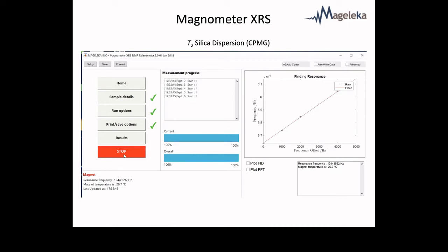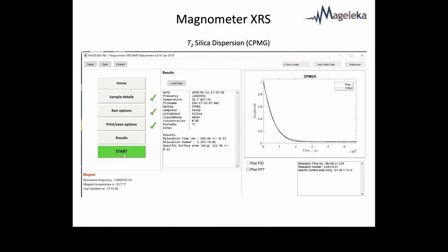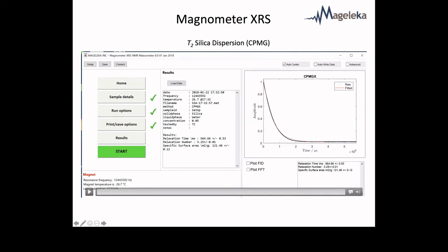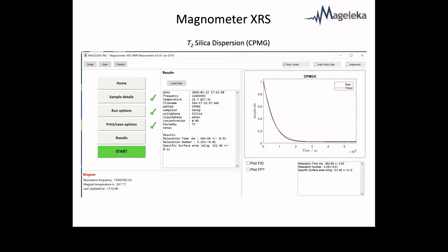Now this is a silica dispersion with a relaxation time of the order of 200 or 300 milliseconds. There, it's done it. So you can see we get a curve, and directly from that we can get the surface area from this calibrated sample. It's 121 meters squared per gram. So you can see it's a very rapid, straightforward experiment. You can do this with settling. You can do this by adding additives. Because it's so fast, you can actually do experiments in the NMR tube and get online data.